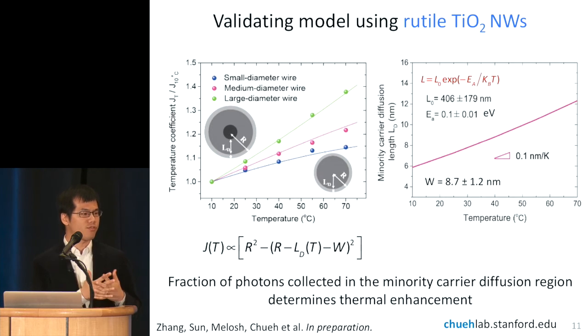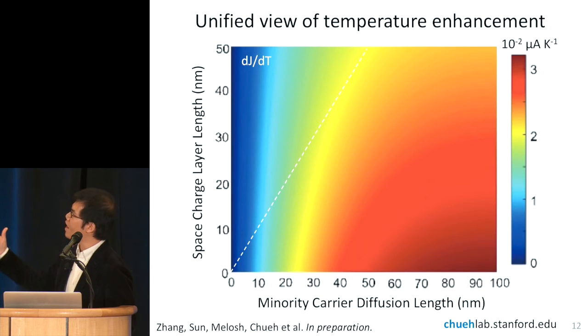So it turns out that the fraction of light collected within the minority carrier diffusion length is what's dictating the thermal enhancement. And here we provide a very unified view of temperature enhancement. This plot shows the performance or the extent of temperature enhancement as a function of the space charge layer width and also the minority carrier diffusion length. And you can see why iron oxide didn't work very well to begin with. The dashed line shows where it is equal.